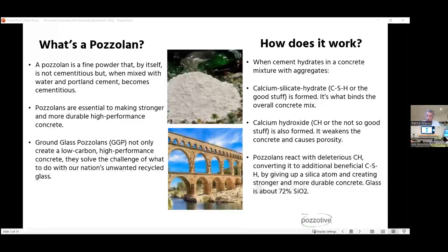What's great about pozzolans, and including glass pozzolans, is that they're high in silica. They give up a silica atom. It bonds with the bad stuff, the CH, and it forms more good stuff, the calcium silicate hydrate. So that's really the magic behind a pozzolan, and why glass is so good. It's very high in silica, and it's very consistent in silica. It's consistent about a 72% level in consumer waste glass.